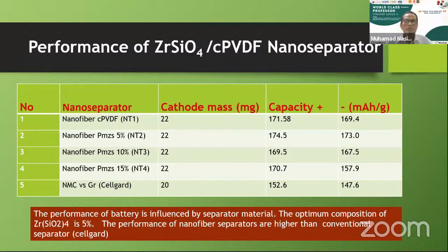And then we try to measure the performance of the separator by using coin cell test. You can see here this is pristine co-PVDF separator. This is zirconia co-PVDF separator with different zirconia content. This is a Celgard separator. You can see here, in general, the performance of nano separator in terms of the capacity is higher than the conventional separator from Celgard. You can see here, this capacity is higher than the Celgard. So the optimum composition is around 5%. We can get capacity around 174 milliampere hour per gram.